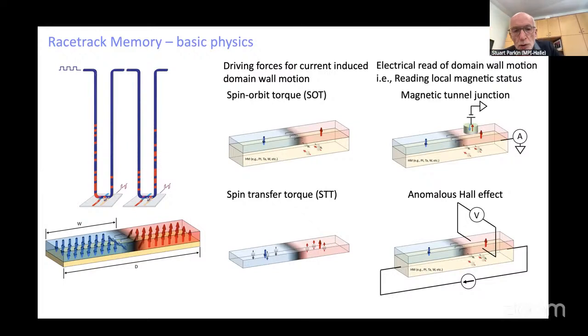If you take just a simple metal with strong spin-orbit coupling, then the charge current is turned into a transverse spin current, which is polarized in a direction perpendicular to that transverse direction and to the current direction. And then that spin polarized current can enable torques to be applied to neighboring magnetic layers into which the spin current diffuses. That's the idea of the spin orbit torque. And it turns out that it's more effective than the spin transfer torques by factors of up to a factor of 10, let's say.